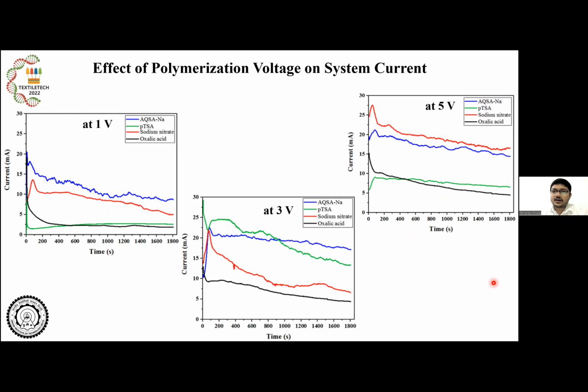Similarly, the current behavior was observed during the formation of polypyrrole polymer. At 1 volt, the current was lower in all the cases. At 3 volts, it was higher, and at 5 volts, it was again highest. We can see the behavior of sodium nitrate, this red colored line, is again similar. It is increasing with the voltage. And in case of AQSA and PTSA, it is again decreasing at 5 volts. So we have used the condition of 3 volts for polymerization voltage, and except oxalic acid, we have compared these three compounds for doping behavior.